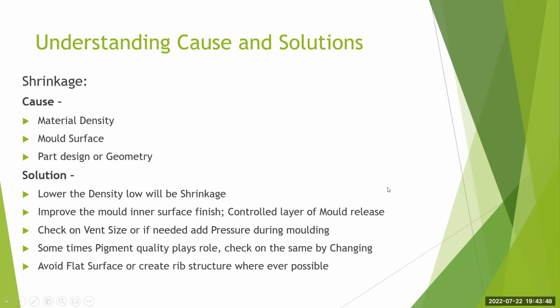Shrinkage: normal shrinkage is 3 to 5%, and it is very important to check the material density if you want to control things. You need to look at the mold surface, and the part design or geometry. These are the three aspects which are basically reasons for shrinkage. And the lower the density, the lower the shrinkage. It is a fact. Improve the mold inner surface finish and control the layer of mold release.